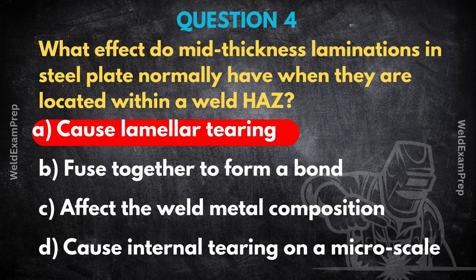Absolutely. The rolling process makes steel strong along its length and width, the X and Y axis, but it's incredibly weak in the through thickness direction, what we call the Z axis. Okay. And if a lamination is there, the material strength in that Z axis is practically zero. You're trying to hold it together across a plane that isn't even fused.